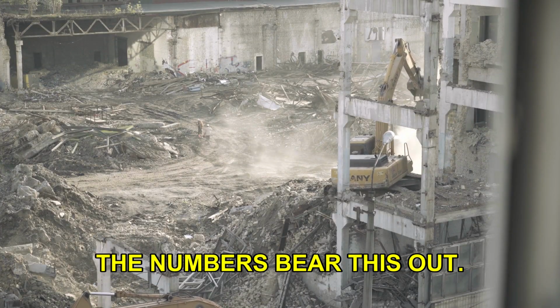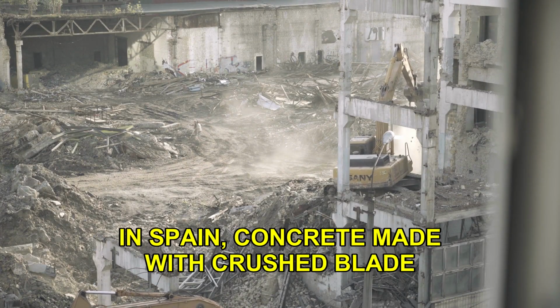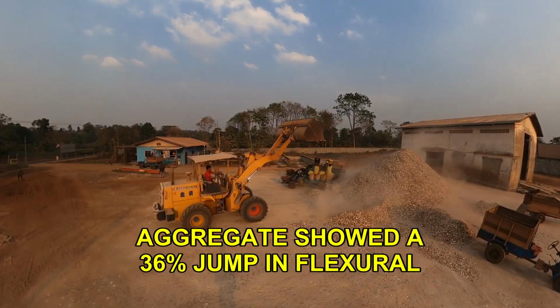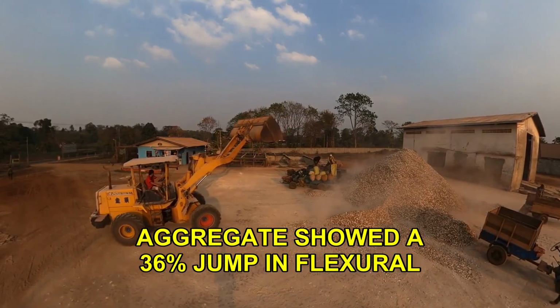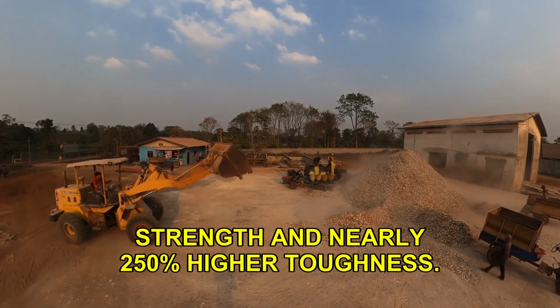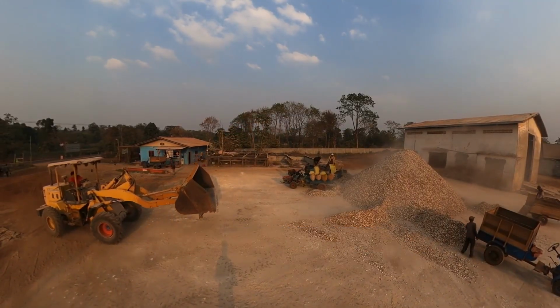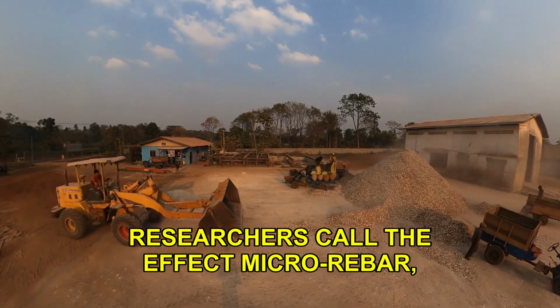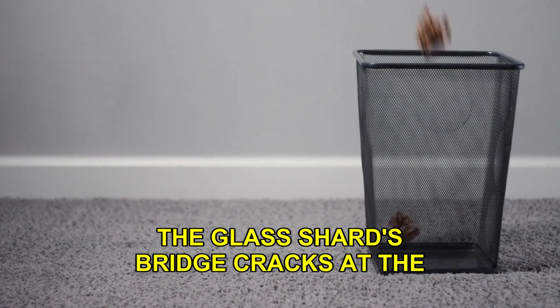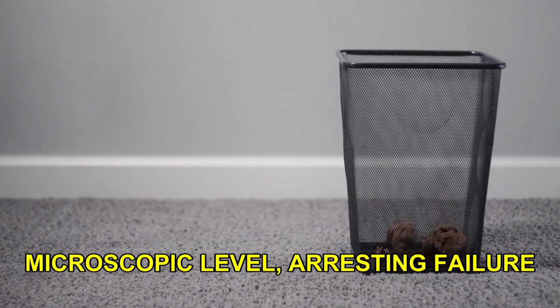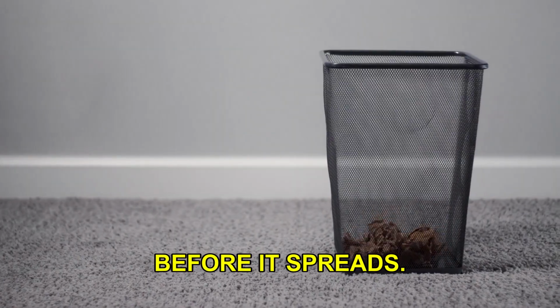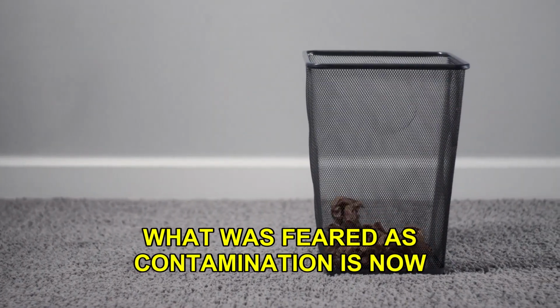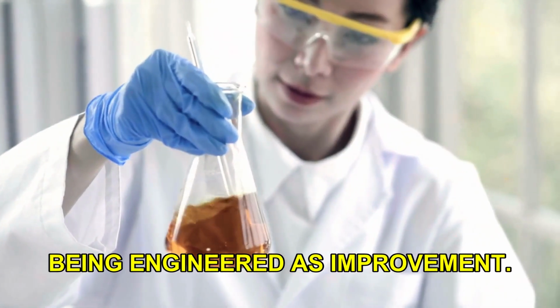The numbers bear this out. In Spain, concrete made with crushed glass aggregate showed a 36% jump in flexural strength and nearly 250% higher toughness. Researchers call the effect micro-rebar. The glass shards bridge cracks at the microscopic level, arresting failure before it spreads. What was feared as contamination is now being engineered as improvement.